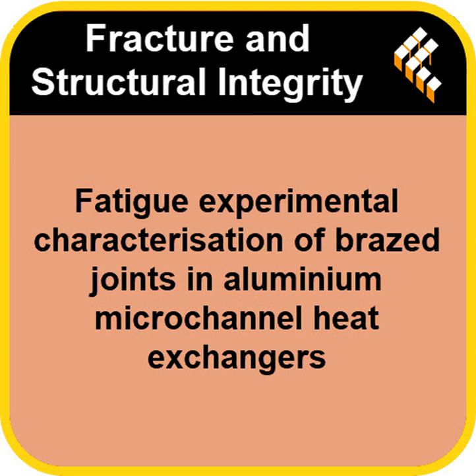So here's the question to ponder. If you could somehow perfect the manufacturing process, if you could achieve a perfectly smooth fillet geometry, eliminating that sharp micro-notch effect, and simultaneously eliminate those flux-related inclusion defects entirely, how much longer could these components truly last? That's the million-dollar question, isn't it? We know the joint is the weakest link, but what is the theoretical upper limit of its strength? If you could remove these known flaws, the geometric ones and the material ones, its potential is still somewhat shrouded by the complexities and imperfections of current manufacturing reality. It suggests the next big engineering breakthrough might not be inventing a radically new aluminum alloy. Perhaps not. Perhaps it's really about perfecting the joint, mastering that critical interface down to the microscopic level.